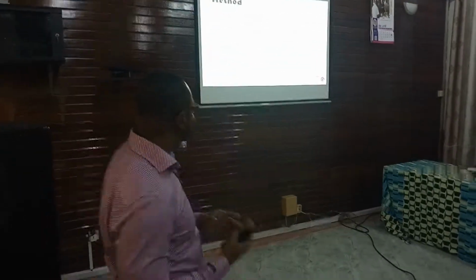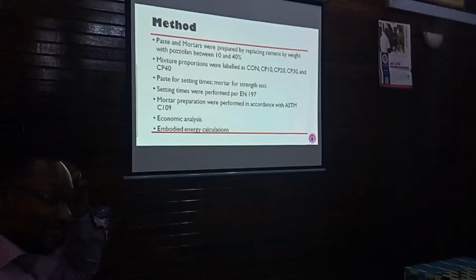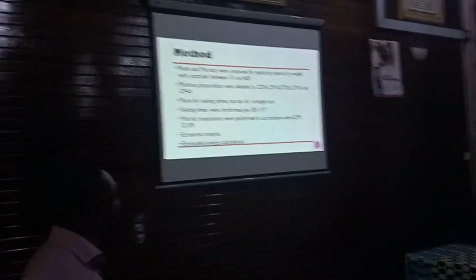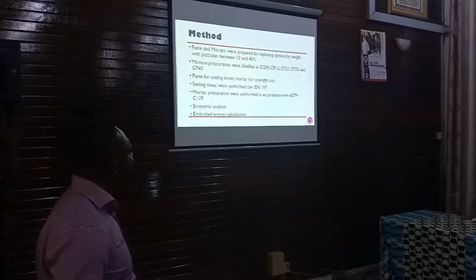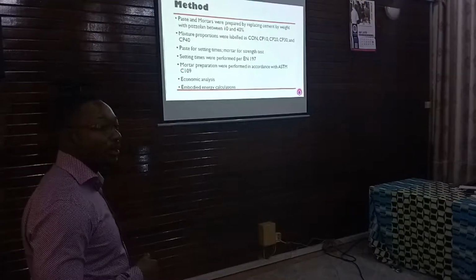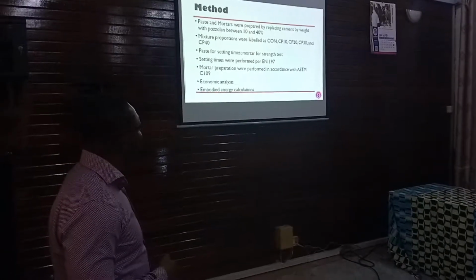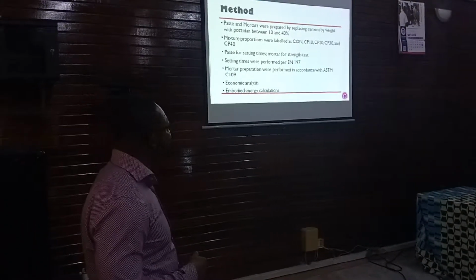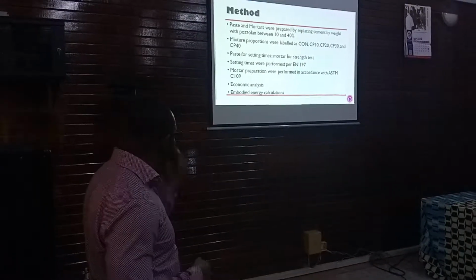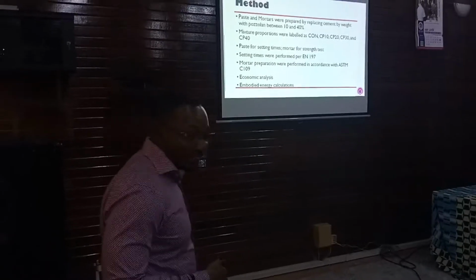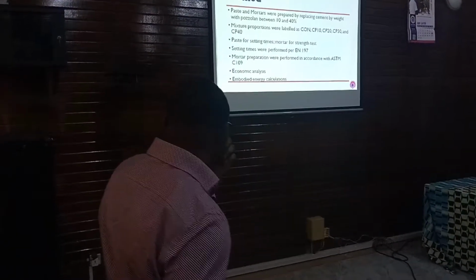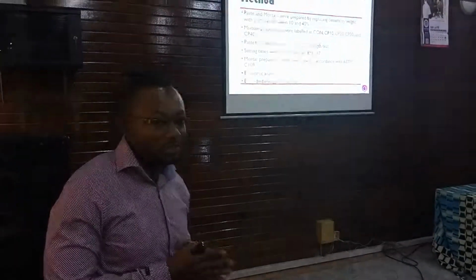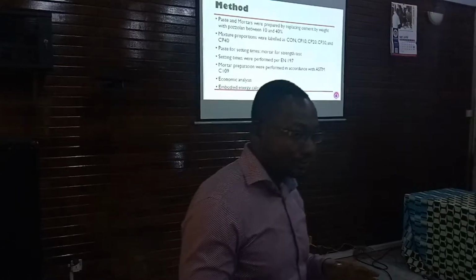Paste and mortars were prepared by replacing cement between 10 and 40%. Now, these were the labels that I gave to it. So you have produced a control mix, and then the control mix being replaced by 10% of pozzolans, and 20% of it, and so on. We produce the paste for the setting times, and then the mortar for the strength. Then we crush it per standard practice, the ASTM C109. I did a little bit of economic analysis from the strength results that I obtained. Then I did a calculation of embodied energy.